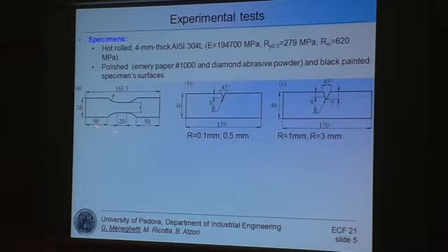Here you see a plain specimen which was used to estimate the fatigue limit and find it experimentally. Here you see a sharply notched specimen we used to define the structural volume size. And here, with the radius of 0.5 millimeters, 1 and 3 millimeters, you see the specimens we used to test the approach.